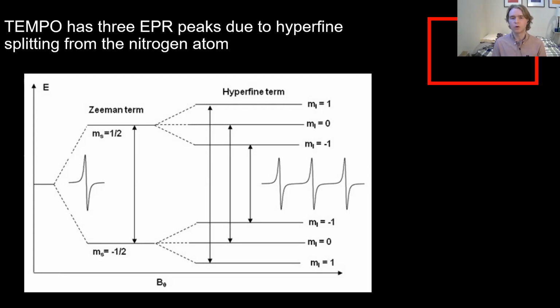And so you might be wondering, well, why don't we see a lot more peaks than just 3? Maybe because there are so many different possible transitions between all of these different energy levels. Well, the reason for that is selection rules. Each of the transitions that are allowed in this system have to follow a very particular set of rules. Those rules being the spin of the nitrogen cannot change, and the spin of the electron must change by 1 or -1. So as we can see, there end up only being 3 allowed transitions between the 3 different nitrogen spin sublevels.